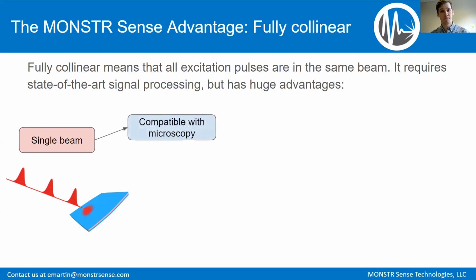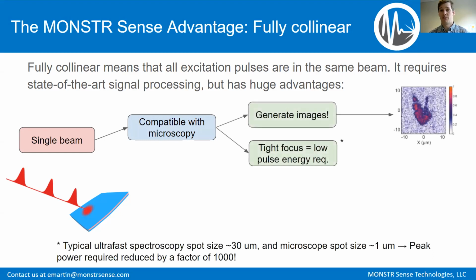So the single beam has the primary advantage that it is compatible with microscopy. Conventional ultrafast spectroscopies have pulses in different beams, meaning that the beams have to cross in the sample, right? So they are a non-collinear type of technique. This is not compatible with using a microscope objective. But if you have a system that is fully collinear, then you can generate images. So say, for instance, using our laser scanning microscope that I'll talk about, we're able to generate ultrafast images, so scan the beam over and get decay maps as a function of position.